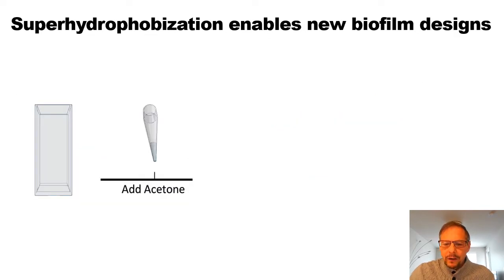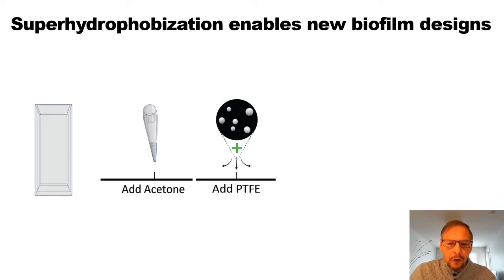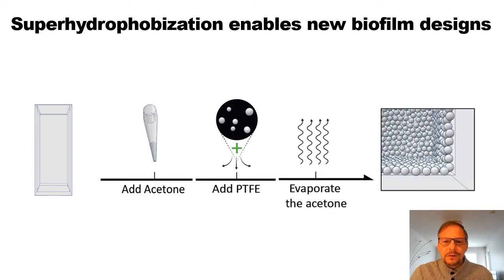So if we take a different route and take any other mold with any shape, like in this case a cube, in this particular case a plastic cube, and we add a little bit of acetone, and we add the hydrophobic particles, in this case Teflon particles, and we let the acetone evaporate, then on the walls of the mold, we're going to see what you see on the right, that is the hydrophobic particles coating the inner walls of the container. And this is where we're going to add the culture medium with the microorganisms so that the microorganisms can have access to the oxygen that is entrapped between the walls of the mold and the hydrophobic particles.